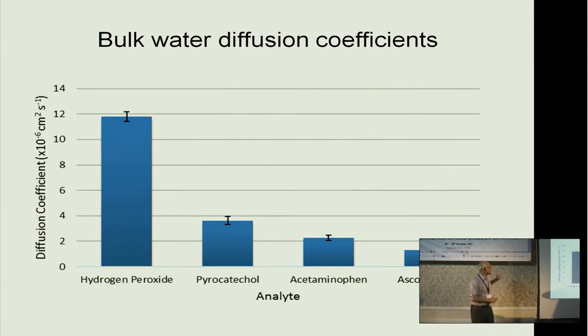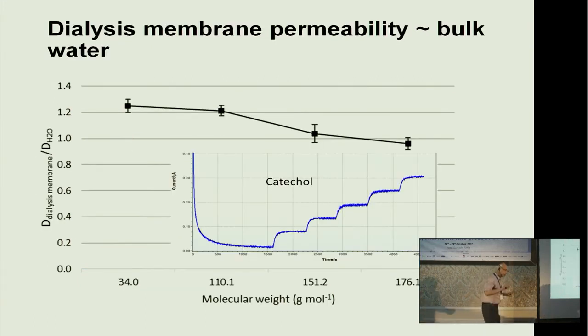This is bulk water diffusion coefficient. They're the same order of magnitude, but they do vary based upon the size of the molecule. I get that, and that agrees with the literature. There's nothing special here. If we take the dialysis membrane, I'm sure a lot of you have experienced those, what you find, and this is the first thing ever done by anybody on this, is that you do get diffusion, which is pretty open. This is for water. The ratio between water and through the dialysis should be 1:1. Actually, it's a little bit out, and it does go down. But the model response is very, very precise and reliable.